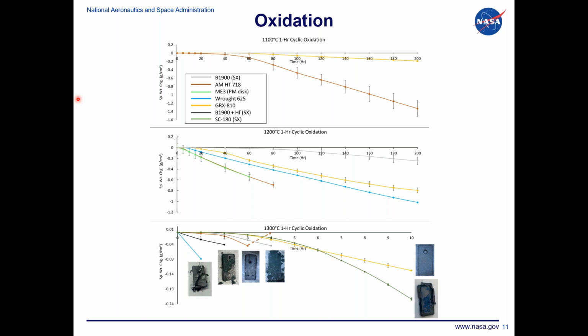We wanted to see where it compares between the alumina formers and the chromia formers at elevated temperature. At 1100 C here, this is 718. This is GRX-810, the yellow curve, and the gray curve here is the B1900 alumina forming single crystal. You can see GRX-810 appears to be closer to that alumina former than the 718 chromia forming alloy, and we expect it's because of those nanoscale oxides. At 1200 C, more or less the same trend. It's bridging the gap between those chromia formers and the alumina formers. But what's interesting is when you get down to the 1300 C 1 hour cycles. This is a very extreme environment.